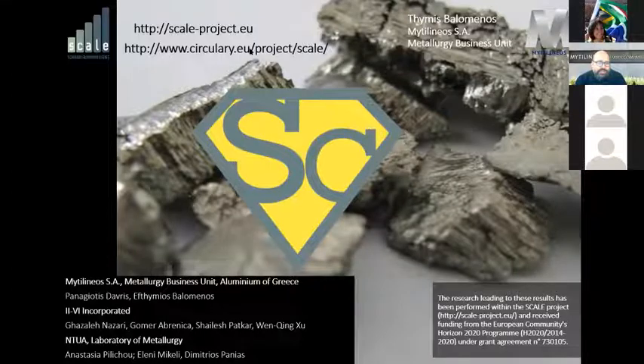So as I showed, for example, in the bauxite residue, the Greek one, you have about 100 ppm of scandium and 100 ppm of neodymium. But the price difference between scandium and neodymium is huge, right? Scandium represents 95% of the value of all the rare earths in there. It doesn't seem worthwhile to go after the neodymium and the yttrium, or the lanthanum and the cerium, or even less so. In any case, of course, this is something we wanted to look into.